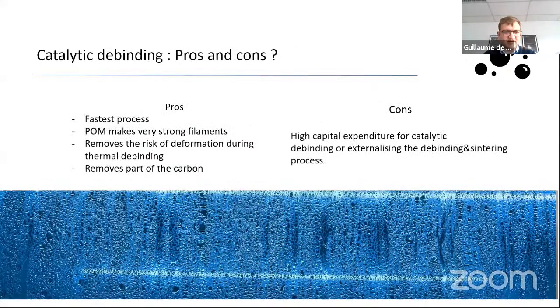What are the pros and cons again? It's probably the fastest process on the market for debinding. POM does make very strong filaments, so they're probably going to be the less brittle filaments on the market also. They're really very strong. It again removes the risk of deformation, and it removes part of the carbon contamination. That's a good point. On the cons, it's quite a high capital expenditure. The catalytic debinding furnace itself is usually industrial equipment. So you can find some lab equipment, but it's still usually quite expensive, which makes it either a significant investment, or there's always a possibility to outsource debinding and sintering, which is quite often done in this case.